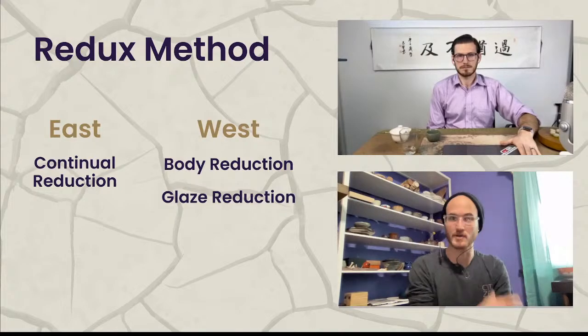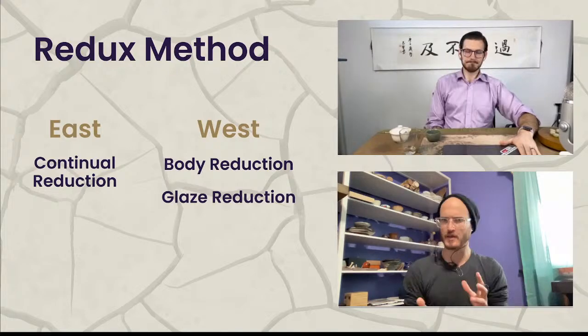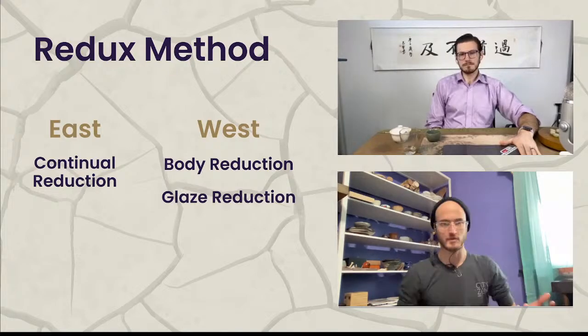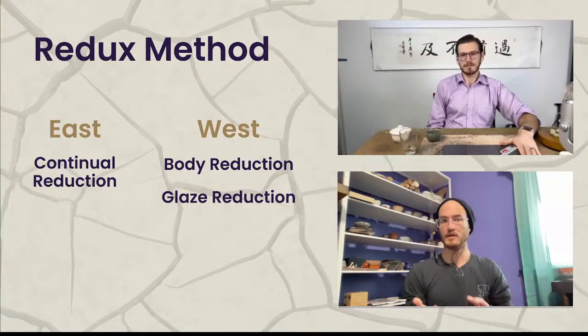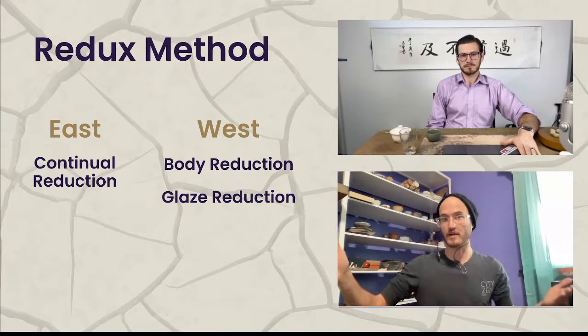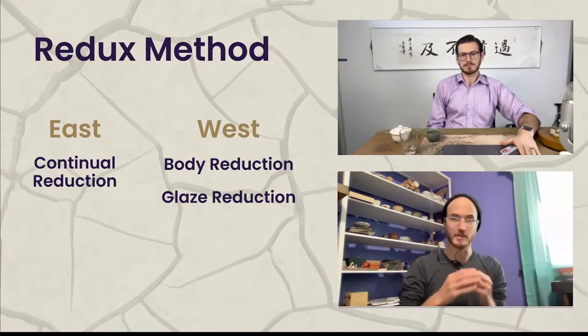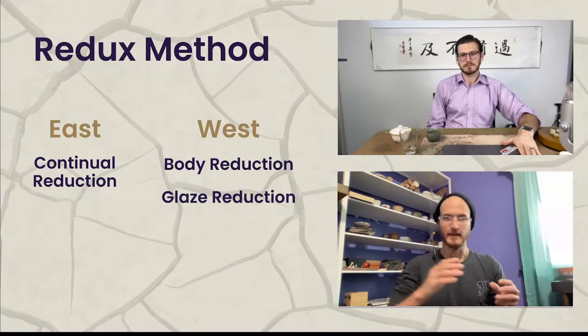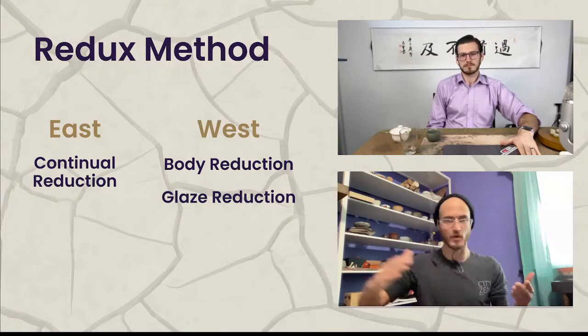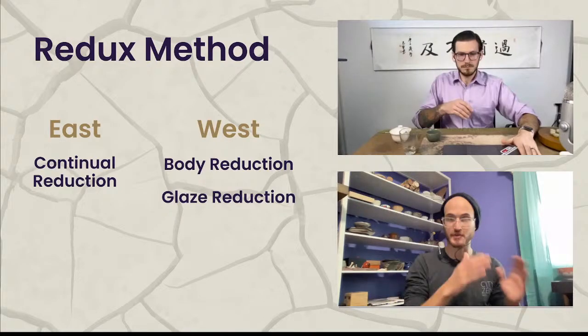So in Taiwan or Korea or Japan, I'm not sure how they do things in China. I haven't been to a studio in China, so I can't say, but I know at least in Japan, Korea, Taiwan, mostly they just do a consistent reduction throughout the firing. So instead of clearing the atmosphere and having oxidation in between these two periods of reduction, it's just a consistent reduction all the way through after a certain point. So let's say after 600 C, when most of your organics have burned out, then you're going ahead and firing with a mild reduction all the way up to where you want a final firing. And then you're just going to stop firing and let everything cool down.